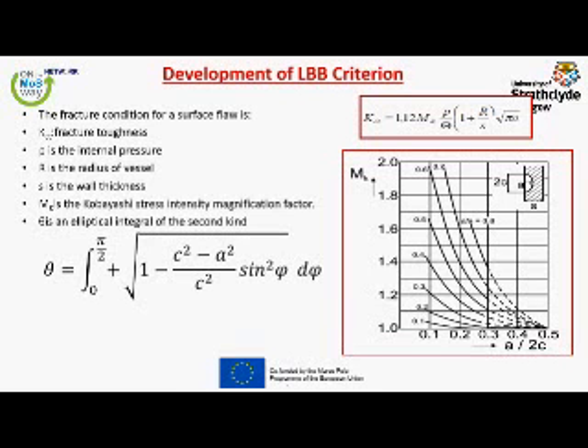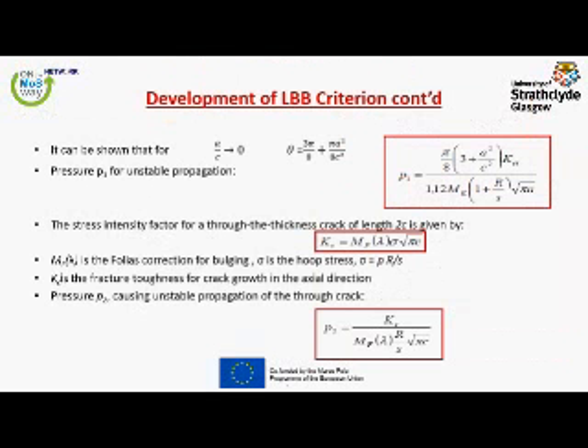The crack will become critical when the stress intensity factor of this crack becomes equal to the fracture toughness of the material in the circumferential direction. So we have this scary looking formula, but don't worry, no need to worry about this. Mk is the Kobayashi magnification factor. You take it from this graph on the basis of the aspect ratio of the crack, and then you can compute the pressure which will make that crack run critical. At the same time, we apply the same idea to find when the through thickness propagation will become critical. We get a critical pressure for the circumferential and a critical pressure for the through thickness. To have this occurring first, this pressure has to be larger than this one.